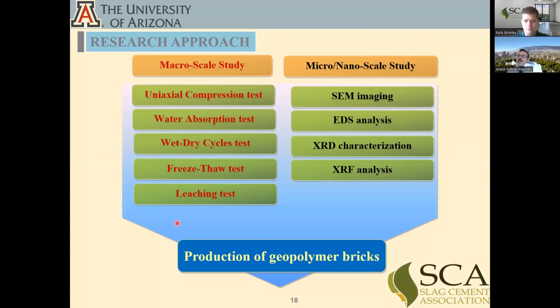To see if we can, we follow this research approach. We did the study at both the macro scale and the nano scale. At the macro scale, we produced the samples and did a bunch of tests on them. We did a uniaxial compression test and a water absorption test to see how much water they absorb over time. We tested the bricks for wet and dry cycles, and also freeze and thaw for cold temperatures. At the end, we did some environmental testing on the brick to make sure that the raw material, like mine tailings that have heavy metals, can be stabilized inside the polymer network of geopolymers, and how successful we are. Then we did some microscale and nanoscale study to see how the microstructure is changing with the chemical reaction we are doing on the mine tailings.